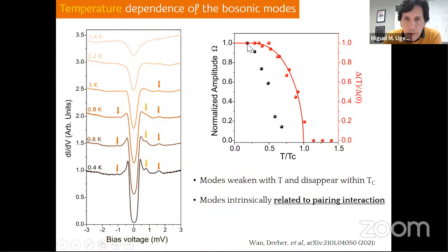So in order to rule out the possibility that these resonances are being weakened due to thermal broadening, here you have the expected evolution of this particular resonance if it was due to thermal broadening. Basically, what this curve is telling us is that these resonances should be visible above the critical temperature if it was just due to thermal broadening. So there is something else that is killing these resonances. The fact that they weaken as we approach the critical temperature means that these modes are intrinsically related to the pairing interaction. And that's why they show up in the density of states.